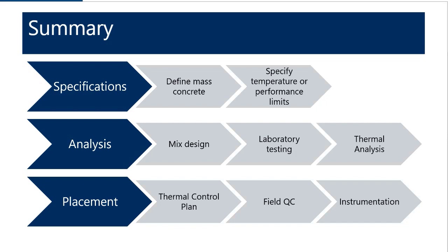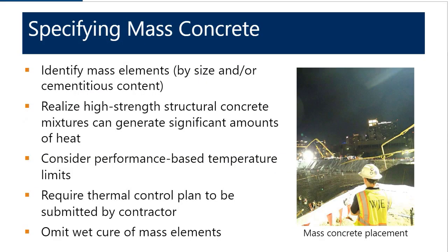As a result, we want to be able to formulate and develop specifications that define the mass concrete. We want to be able to analyze it, prepare a thermal control plan, and then use those things to help with the concrete placement efforts. If you're a specifier, some of the key things you need to be thinking about when specifying mass concrete is identifying the mass elements. This can be done by size, geometry, cementitious content, surface area. There are different ways you can do it, but it needs to be clearly identified in the project plans and specifications such that the contractor can plan it and bid it and execute accordingly.